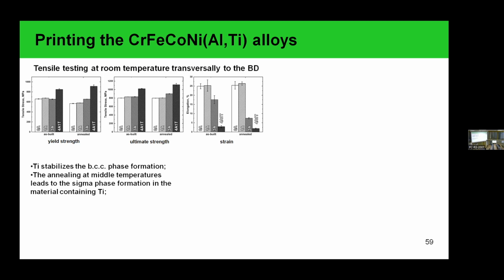In case of the material with titanium, we see the increase of strength in case of the as-built material, and further with annealing, we see an additional increase in strength, but we totally lose the ductility even at the as-built and annealed state of our material.